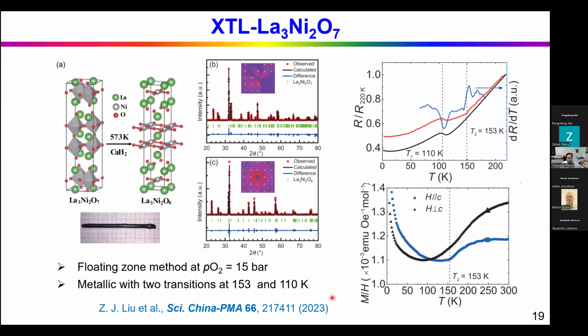And until last year, Professor Meng Wang's group in China synthesized this 327 single crystal by using the floating zone method under oxygen pressure of about 15 bar. And they grew the single crystal. It looks pretty good. And the resistivity shows a metallic behavior with two transitions, one around 153 Kelvin, another at 110 Kelvin. This is the susceptibility, minus susceptibility.